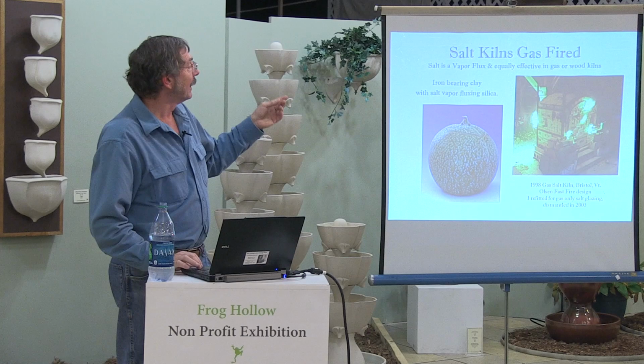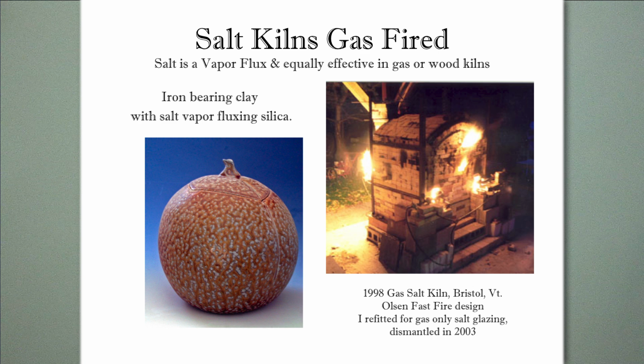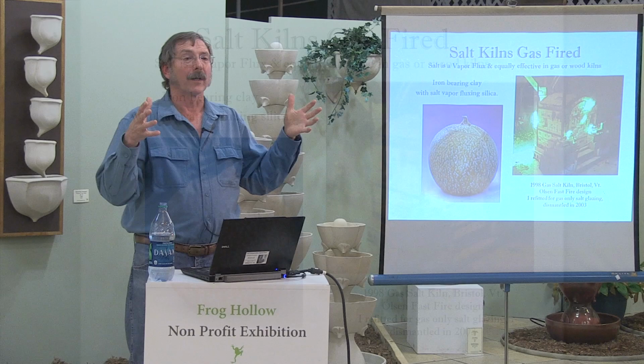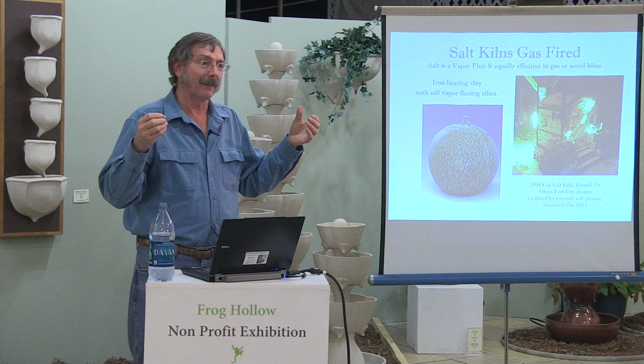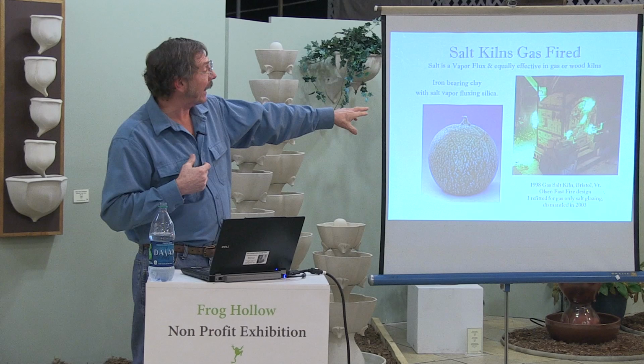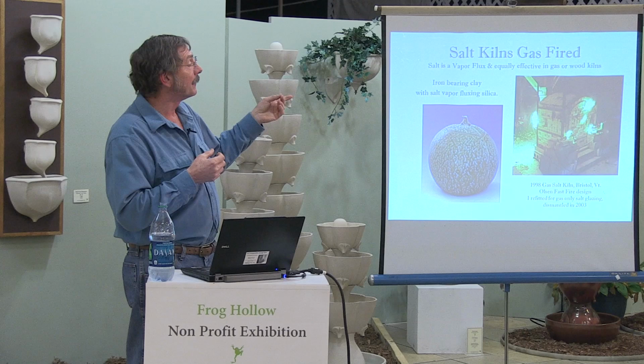So I did have a salt gas kiln, which burned out after about 10 or 15 firings. I salt really heavily, and I built this kiln out of insulating fire brick, which was great for holding the heat in. But insulating fire brick, and we'll talk about bricks in a minute, is very porous. It gives great insulation and is wonderful to fire with, but it will also absorb sodium and kind of just dissolve from the inside out. So for a number of years, I fired with gas. This is an Olsen Fastfire wood kiln that I converted to gas and did salt glazing, and that really got my heart going with salt glazing.